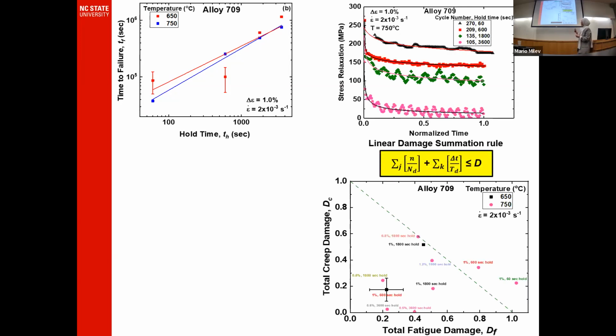So this is what happens with hold time: the stress relaxation plotted versus normalized time. At different hold times, we have 60 seconds, 600 seconds, up to an hour. It all follows the same trend in which once the hold time or creep damage starts, the maximum stress drops and then follows a steady state behavior, for a longer period because of longer hold time. That's why the material is subjected to stress for a longer time, and that's why it fractures.